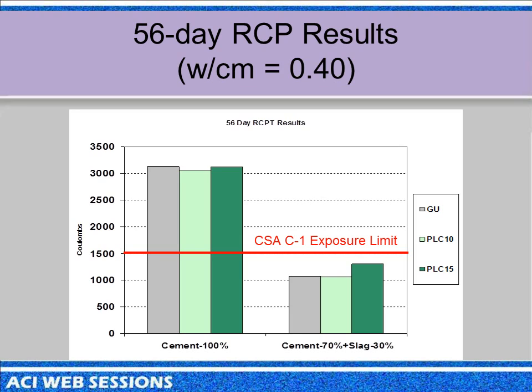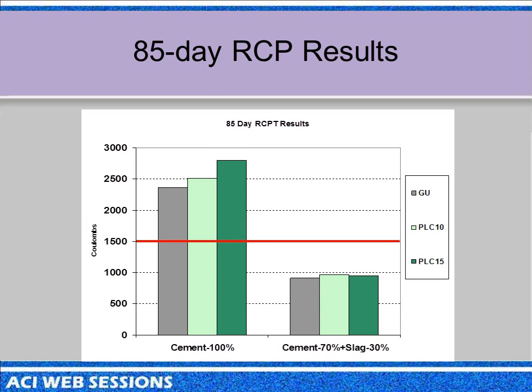And in terms of durability issues, just to show some rapid chloride permeability, the ASTM C1202 results, we have a requirement in the Canadian standard for 1,500 coulombs at 56 days for extreme exposures, such as de-icer salt. And these are Portland cements with increasing amounts of limestone here. And here's with 30% slag. And you can say, well, gee, the 15% is not quite as good at 56 days. We wouldn't use 15. We allow 15, but of course with controls, you're looking at 12 to 13% limestone in these cements. But at 80 days, 85 days, they've still improved, and they're down below 1,000 coulombs, and you don't see the difference, even with those same mixes at 85 days.